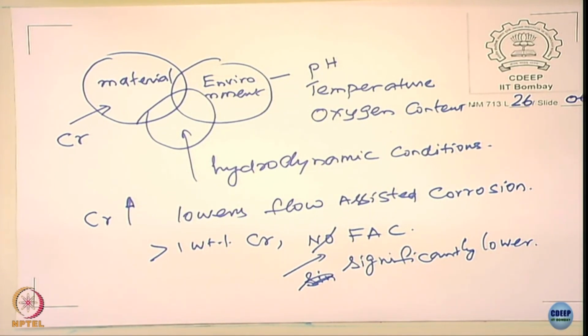It does not occur in stainless steel, and stainless steels are not used very extensively because they are expensive process materials. So in economizers, many of the units we discussed here are not made up of stainless steels. Earlier they were made of simply carbon steel. Now people go for chrome steels, 1 chromium or even 2 1/4 chromium, but 1 chromium is quite common. These are the materials people now use in order to prevent the flow assisted corrosion of metals.